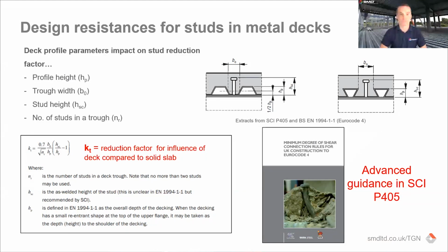I hope that helps. There is more quite advanced information in P405, which is an SCI publication, and that gives you more guidance on where you can put the mesh. So it gives you resistance values for mesh low and high in a slab. Typically in the UK, we tend to put it high in the slab, but you may wish to increase resistance by dropping the mesh lower, which can give you some improvement in KT values.